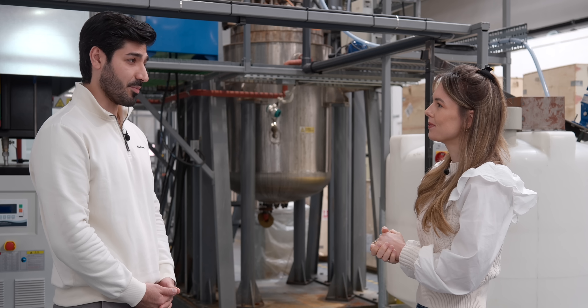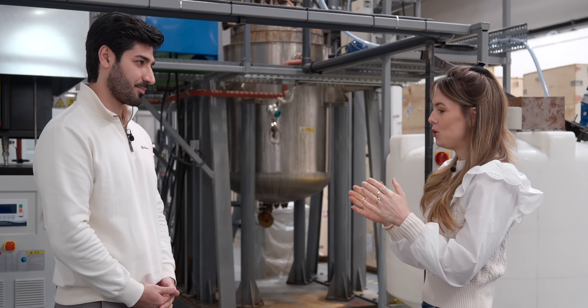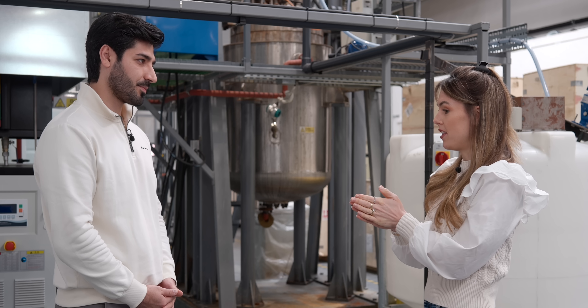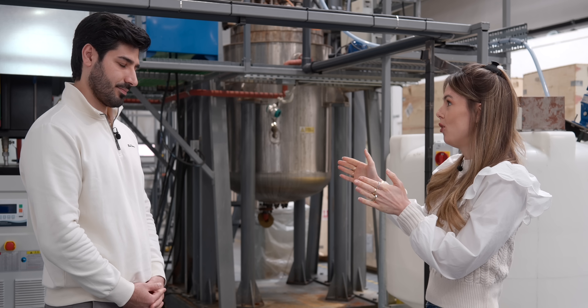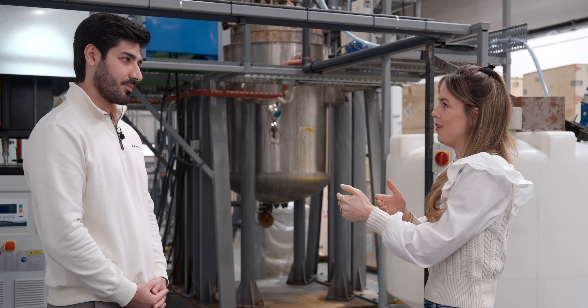The higher the manganese composition — the highest we've made is 80% — that allows you to push the boundaries up to that 20% boost. So 20% more energy means you could either go 20% further with the same battery, or use a smaller battery to go just as far. That 20% energy density boost ultimately refers to a 20% improvement in range, so you can either have the joy of lighter, more condensed batteries, or outperform conventional LFPs.